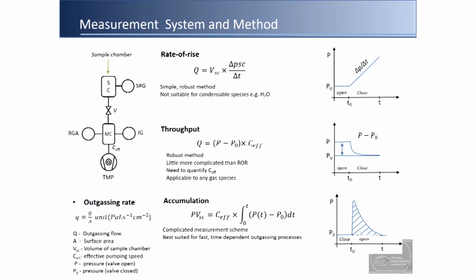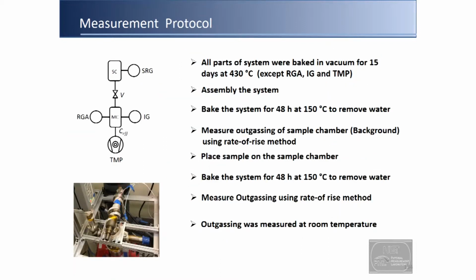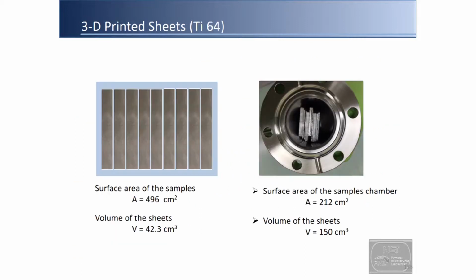So the basic measurements we've done are the same ones everyone in vacuum does: the rate of rise, the throughput, and accumulation type measurements. We can go over these if you're interested. Again, the measurement protocol is the standard one people have been doing in vacuum science for a long time, and it's very laborious and time consuming. Basically, you're trying to get rid of all the water and hydrogen gas that's in your sample holders. Once you do that, then you can look at what's coming off of your parts.